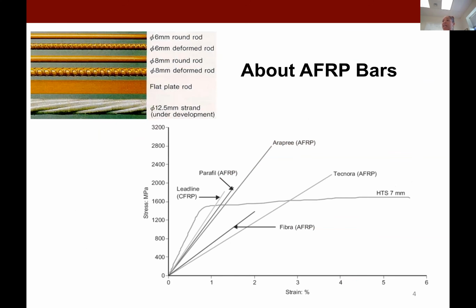So just a little bit diving deeper into the AFRP bars. There's several different types that are commercially available. The AFRP is what I focused on. So as we know, it's a little bit less stiff than the CFRP, the carbon, but stiffer than the glass. Technora is a type that was more fabricated out of Japan. You can see again a lower stiffness there. So we use the AFRP type, and then we can compare it to the steel.